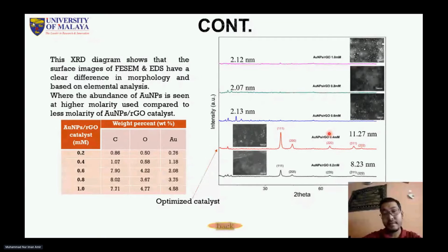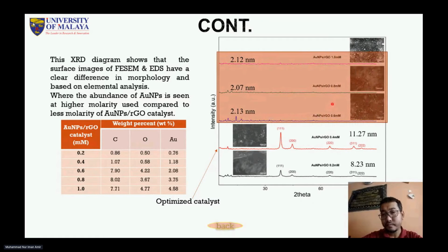concentration of the catalyst. Besides that, based on this XRD analysis, we found that using a higher concentration of gold gives a smaller particle size compared to the lower concentration. This is due to the amount of citrate used during the synthesis process, which was saturated and utilized more at higher concentration of gold.